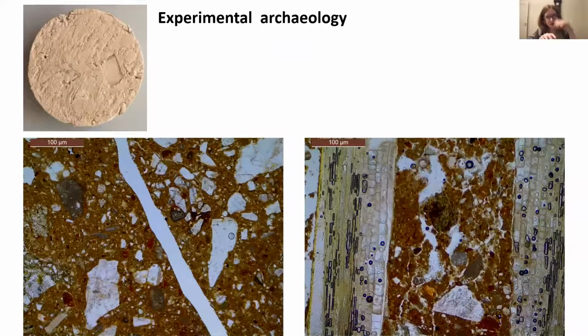So I ran some experimental archaeology, creating briquettes with both barley chaff and seagrasses. And here you can see the morphological difference. I thought this was quite nice because it's a bit self-explanatory, the difference of void between the chaff, the one that you have on the left, and the seagrasses. The seagrasses are not completely burned because the temperature we reached with this specific experiment that I conducted when I was a fellow at the Wiener Lab was not high enough for the seagrasses to burn, just to burn the chaff. So why were people actually using the seagrasses?